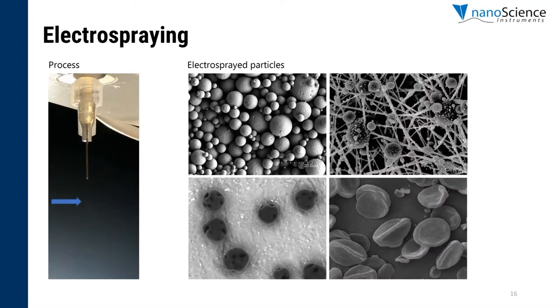When the solution viscosity is low, instead of fibers, we can obtain particles. The concept is the same as before, but it is called electrospraying. This technique is used to create particles in the micro and nanoscale. With a lower viscosity, low entanglement will happen during sample processing, meaning that you're going to be creating particles instead of fibers. The process is seen in this left image.